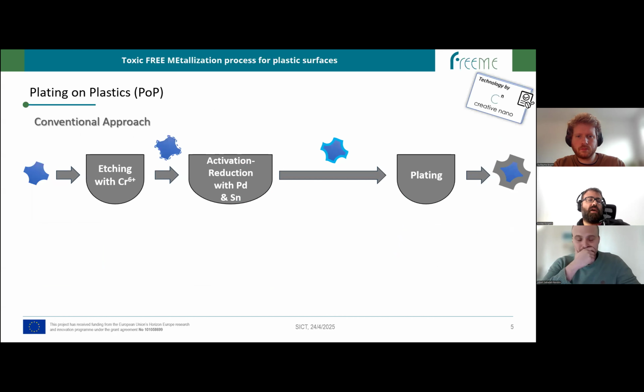And in fact, the conventional approach already includes these three main steps, where the plastic here on the left is etched by hexavalent chromium, and then the etched surface is activated and reduced by using a palladium tin mixture, and then the prepared surface of the plastic is then plated at the final stage.